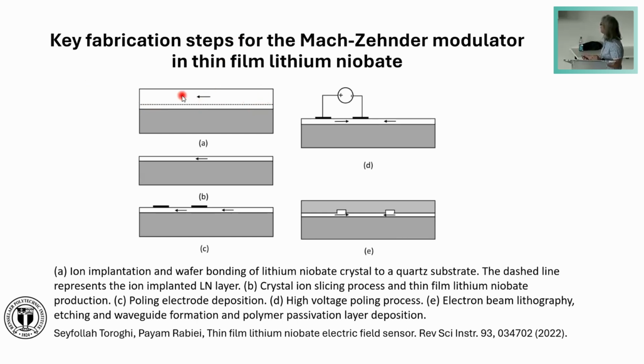Then the ion implanted crystal is wafer bonded to the substrate, like for example the fused silica, and then the bonded structure is heated. And then as a result of thermal expansion, the crystal breaks at the ion implanted layer. This is also called the crystal ion slicing process, and this basically just pops off. And then we have the thin film lithium niobate on the insulating substrate like the fused silica.